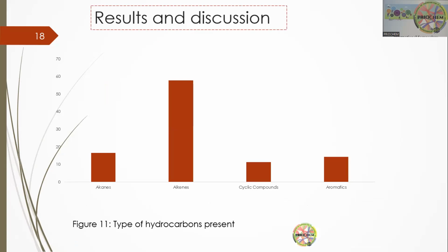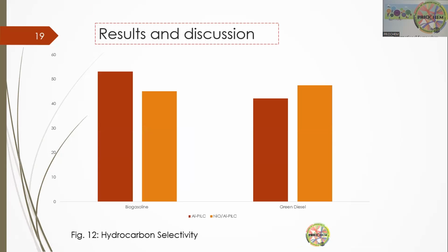And here is the type of the hydrocarbons present in the products. We have alkanes, we have alkenes. If you can remember, in our molecular profile of hydrocarbons oil, we have almost 68% of the unsaturation. So that is the reason we're having this high amount of alkenes and less amount of alkanes. And another issue is that the alkanes can be from the decarboxylation, and these alkenes can come from decarbonylation. We still have cyclic compounds and aromatics, and it has been reported that these reactions also take place alongside the deoxygenation reaction.